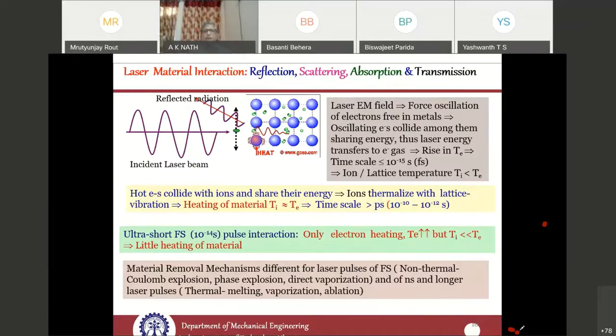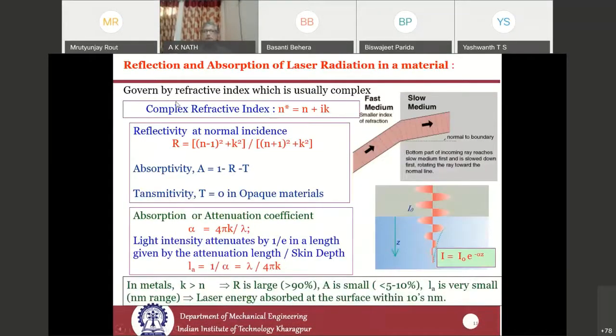But when you consider metal, where there is a lot of free electrons, the refractive index is complex, having a real part and imaginary part. Depending on this refractive index, reflectivity is given by an expression, and absorptivity is nothing but 1 minus R, the reflectivity and transmittivity. In case of metals, which are opaque, transmission is 0, so absorptivity in the material equals 1 minus R.